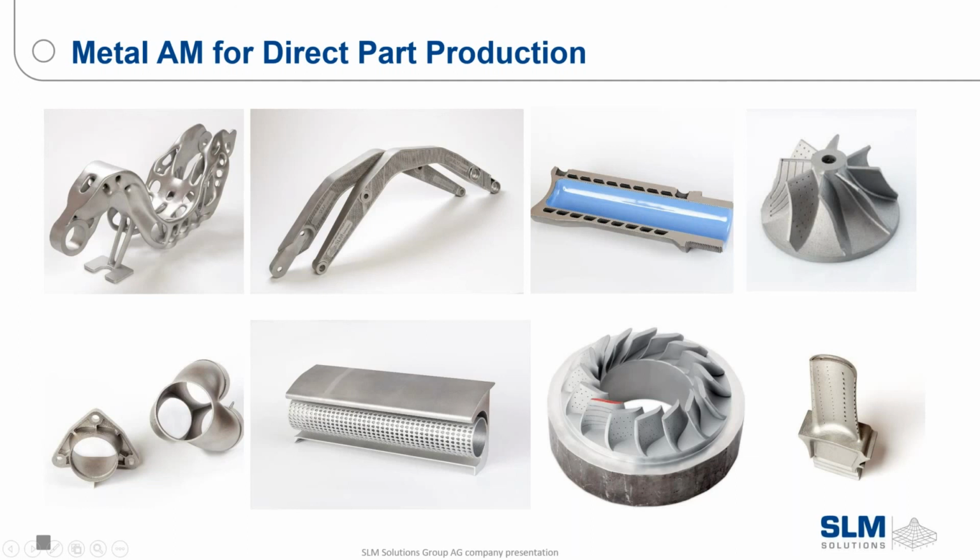So it's about 6 to 8 Ra for surface roughness on that, or 6 to 8 microns, especially for the side walls, which can be very smooth. The grit blasting or surface blasting can clean it up a little bit more, but it's not really going to reach a mold level surface finish. But something like electropolishing would actually produce the surface finish required for a mold level piece.